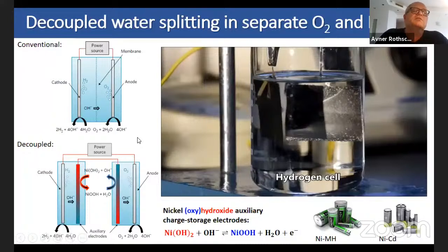And the way we solve this is by introducing, in addition to the anode and the cathode, an additional set of two electrodes. We call them auxiliary electrodes, which are made of this nickel hydroxide, oxyhydroxide redox couple that is used in nickel metal hydride and other rechargeable alkaline batteries. And the idea is that one of these electrodes is charged in the hydrogen cell that produces hydrogen. The other one is discharged in the oxygen cell that produces oxygen. And once they reach the full capacity, you simply swap them.